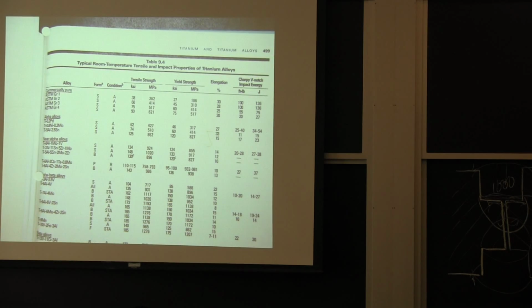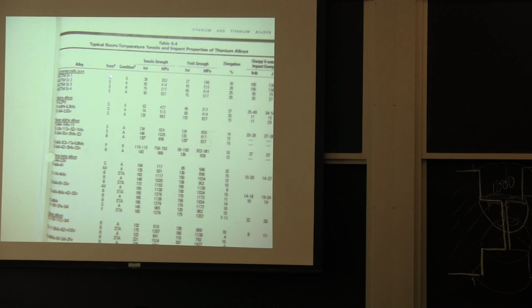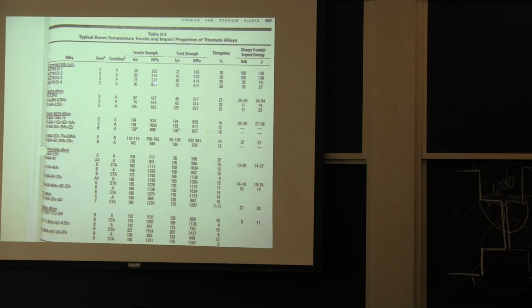I had mentioned there are relatively few titanium alloys out there. They have very good strength in general. The pure titanium may be fairly low strength. This is grades 1, 2, 3, 4, and that's just increasing the oxygen from about 1,000 ppm up to 4,000 ppm or so, and you can see the strength doubles as you add the oxygen. Your ductility should go down 30% down to 20%. 20% is not bad ductility, okay?